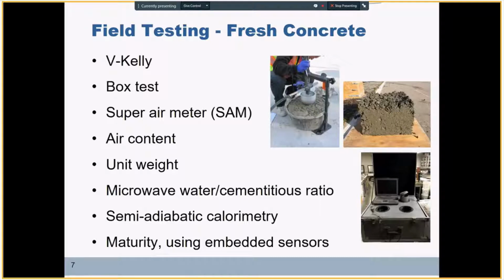We determined the actual water cementitious materials ratio on site using the microwave test. We also did semi-adiabatic calorimetry to monitor the heat of hydration of these concrete mixtures, and used maturity sensors to have a good idea on strength development of these two concrete mixtures.